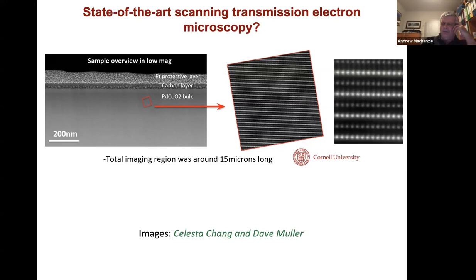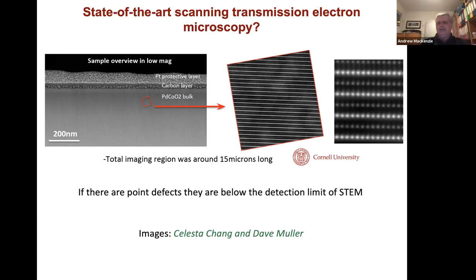But the resolution's not that great there. Actually, for point defects, the resolution's of the order of a percent. Within that resolution of a percent, again, they simply didn't see any. And so it's below the detection limit of STEM.